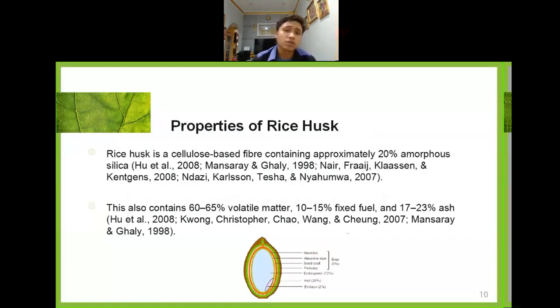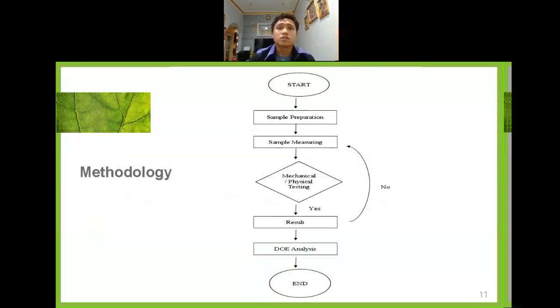Then we go to the properties of rice husk. Rice husk is a large-scale agriculture waste. It is a significant byproduct of rice husk milling and the agrobiomass industry. Rice husk is a cellulose-based fiber containing approximately 20% amorphous silica. And then from the next certificate that I get, this also contains 60 to 65% volatile matter, 10 to 15% fixed fuel, and 17 to 23% ash. This is all I get from the articles.